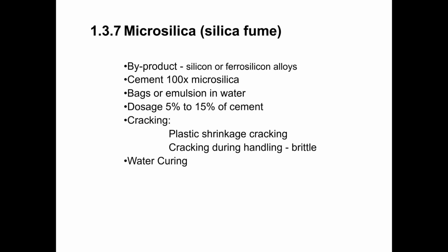Oftentimes, it will be batched from biodegradable pre-weighed bags. So the bags go into the mixer. That way the mixer can be closed and sealed before the bags are broken open, and the microsilica becomes airborne. It's contained to the mixer. It can also be batched as an emulsion in water. Mixed with water, it doesn't dissolve in water, but it can be emulsified in water.